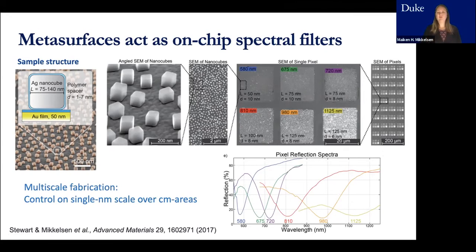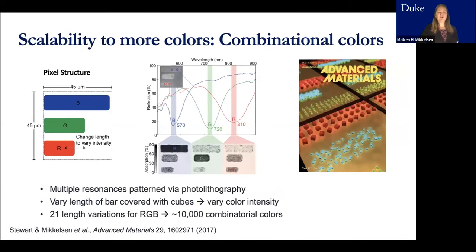Each of these is done with a photolithography step. So we are combining layer-by-layer deposition and photolithography, so that we can deposit cubes to adhere in only one area and not another area. But if you want to make a lot of colors, more than these 6 or 20 or so, it might get pretty cumbersome. So we also came up with combinatorial colors, similar to a red, green, and blue scheme, where you're varying the fill fraction of the different color bands within a pixel. That allows you to create combinatorial colors, and we showed you can get up to about 10,000 of them.